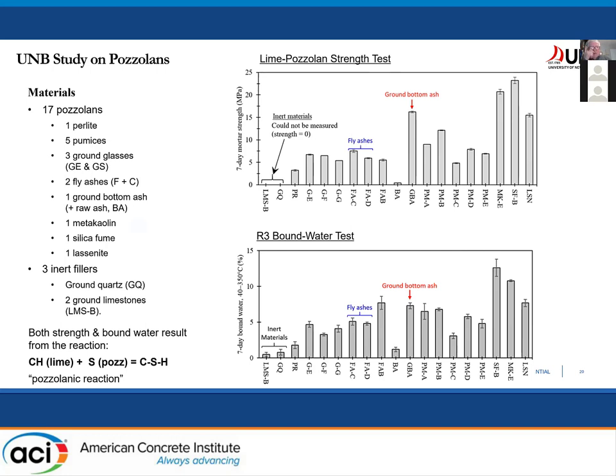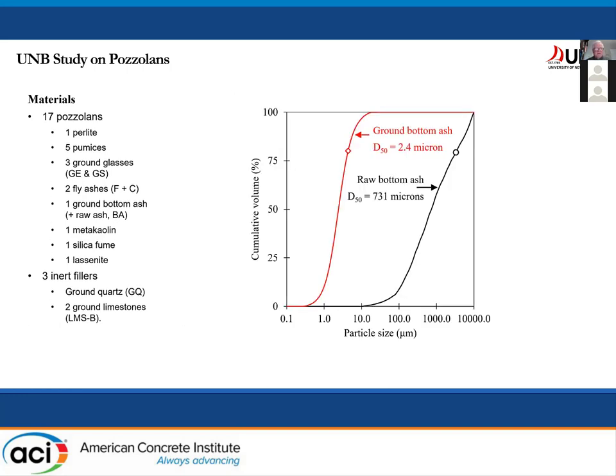And this just shows some 7-day mortar strengths. The ground bottom ash is shown in red, as indicated there. Some fly ashes are shown in blue there. We've got some inert materials in there and some very reactive metakaolin and silica fume and things on the right. But you can see the ground bottom ash is giving good 7-day strengths. And we compared it to the ASTM C1897 bound water test that came in last year, the so-called R3 test. And you get a good relationship.